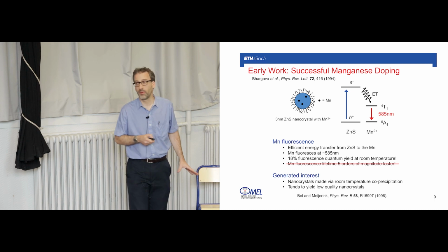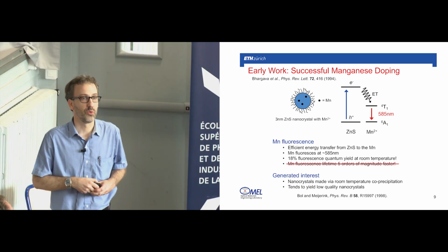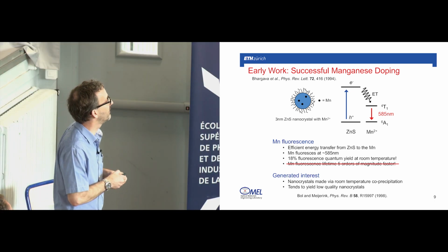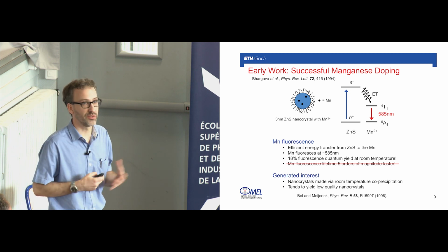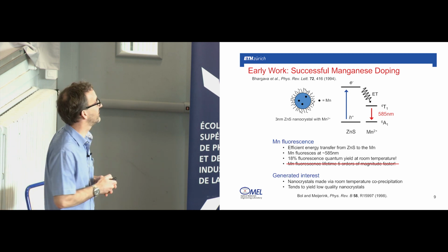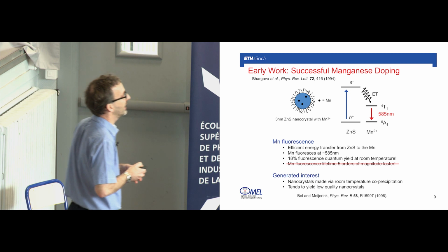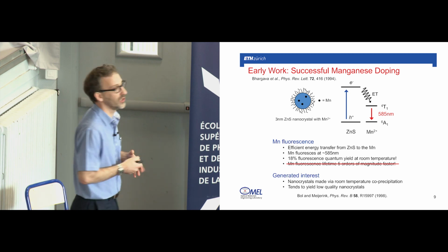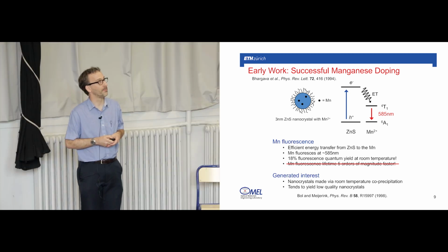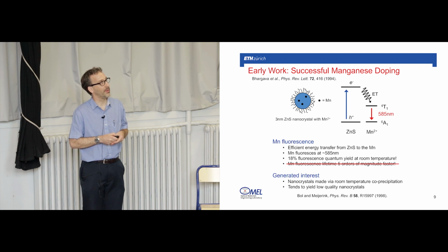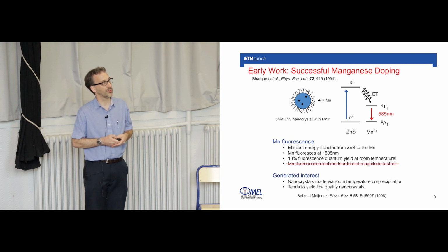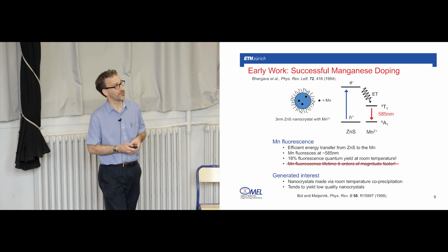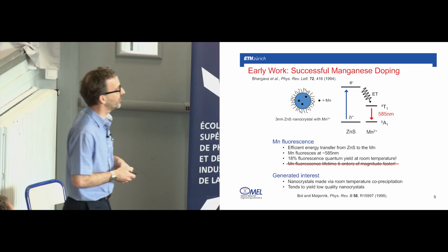Now, the next step in the story is that there was a paper in 1994 by Bhargava et al. in PRL that really caused a lot of excitement, because it was an example of successful doping, not with an electronically active impurity, but with manganese as the dopant. In this paper, they made 3 nanometer zinc sulfide nanocrystals, and they proved by several different techniques that the manganese was incorporated.